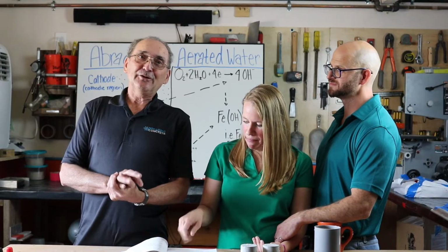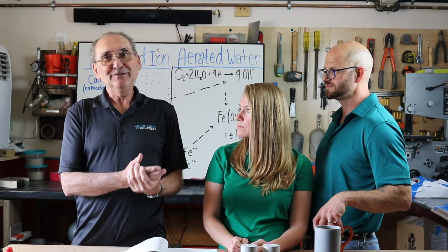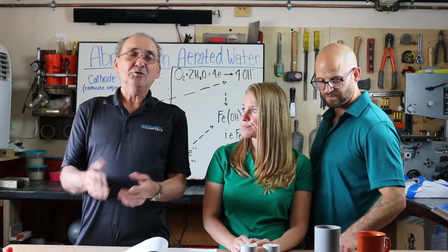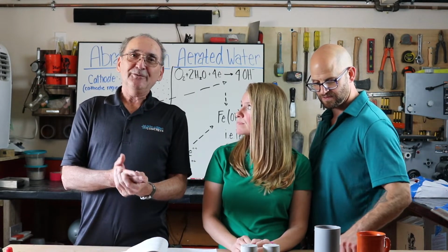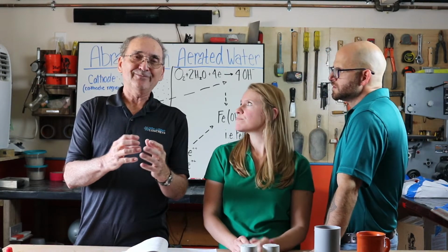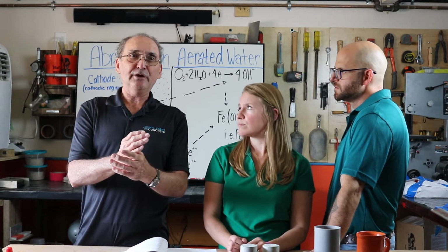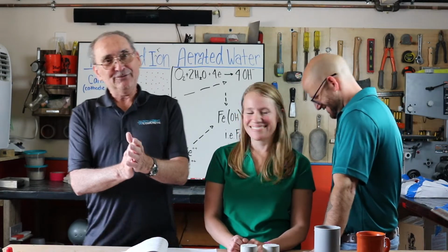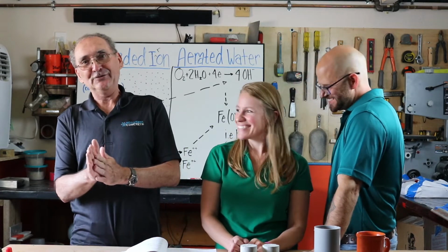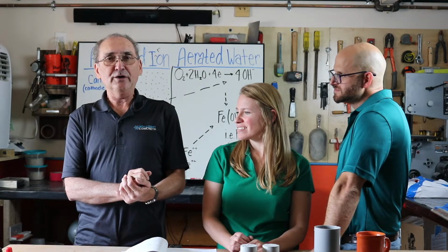All right, so we design reinforced concrete with reinforcing steel. And as John said, bad things can happen. Why are they bad? Well, corrosion, when it starts to occur, has an increase in volume. What is an increase in volume? It's tension. Is tension bad? Tension is bad. Concrete just doesn't like tension. So if we get an increase in volume, that's tension, that's a bad thing.